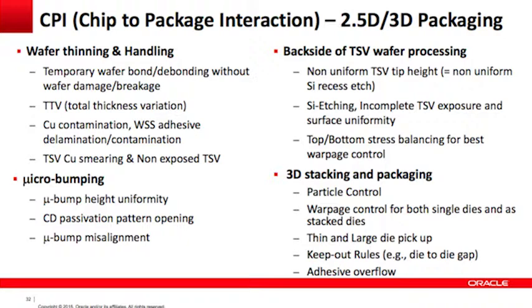And with all those 2.5D packaging, there are other areas and challenges we need to look at, like wafer thinning, handling those 100 micron thin wafers, and micro bumping technologies, what is the joint uniformity. One wafer, even one chip, has over 20,000 micro bumps. So the bump height should be controlled within 5 micron. Otherwise, some bumps are going to be open and some very compressed, so open or cold joint. And the backside of TSV wafer process is another process challenge.